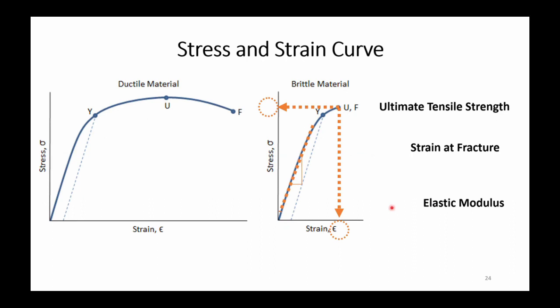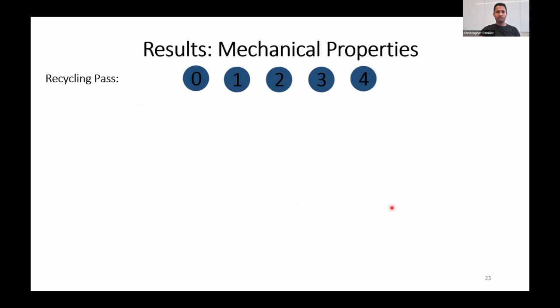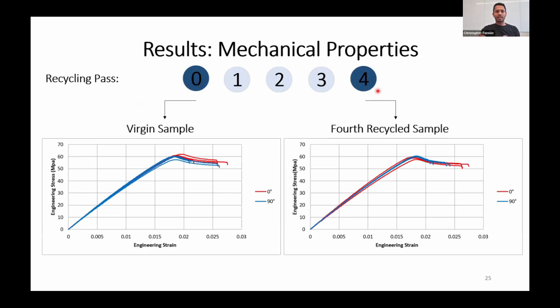So keeping that in mind, we did all of these tests for version 0, and then first pass, second pass, all the way to the fourth pass of recycling. And we looked at these stress and strain curves. We were surprised because usually whenever you print in different orientations, 0 degree and 90 degree, one would be about double the values of the other one, but here we did not see any significant difference between these two.